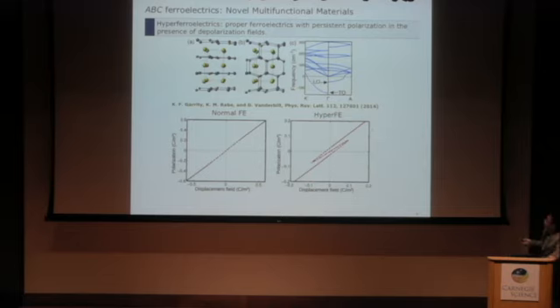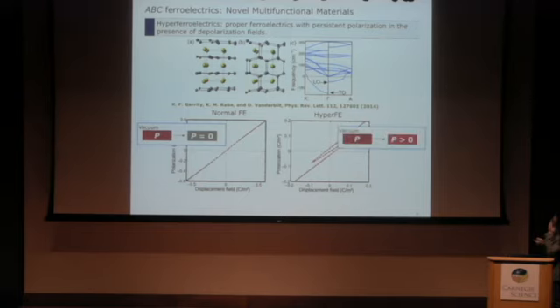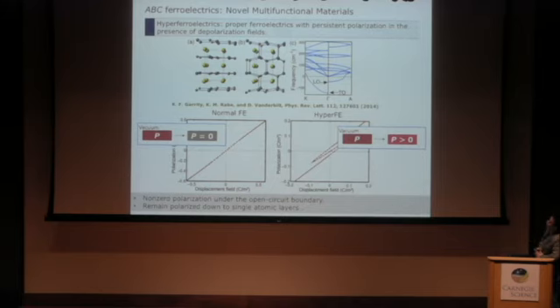So in this paper, I think this figure illustrates the difference. For normal ferroelectrics, this is the polarization as a function of displacement field. As you can see, this line crosses the zero point. So what's happening is when you put a slab of ferroelectric material in vacuum, because of the depolarization field coming from the surface charges, it will kill the ferroelectricity. So under this very ideal open circuit condition, a ferroelectric thin film will be non-polar. I think this is now well established. In contrast, when you put a slab of hyperferroelectric in vacuum, it can still be polar. And so this really demonstrates the robust ferroelectricity supported by ABC ferroelectrics.